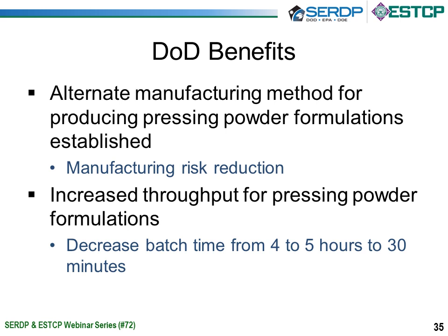So with this process, there are some DoD benefits. First of all, we have identified an alternative manufacturing method for producing pressing powder formulations. This is a manufacturing risk reduction for the production of these types of materials. Not only that, but we have increased the throughput for the pressing powder formulations. Typical slurry coating of these materials takes about 4 to 5 hours to complete, where we have now reduced that manufacturing time to between 20 and 30 minutes. Slide 36, please.